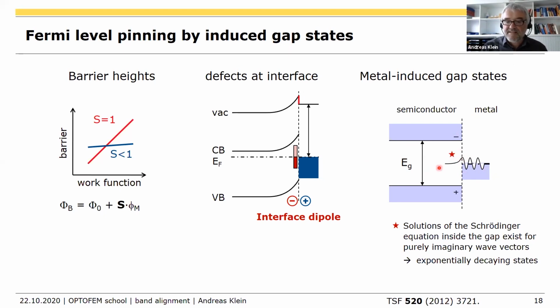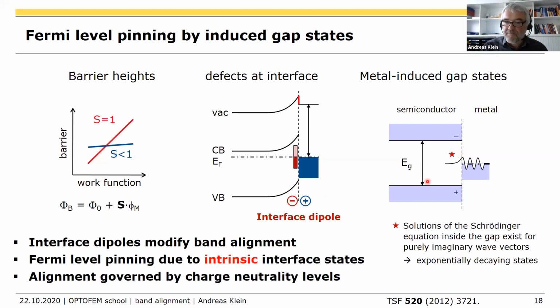So that means you get some electronic states there. And these are the metal-induced gap states. And these are intrinsic interface states. These cause these intrinsic interface states. That's something you cannot avoid. If this is true, then the band alignment is governed by the charge neutrality levels, which is a feature of these states.